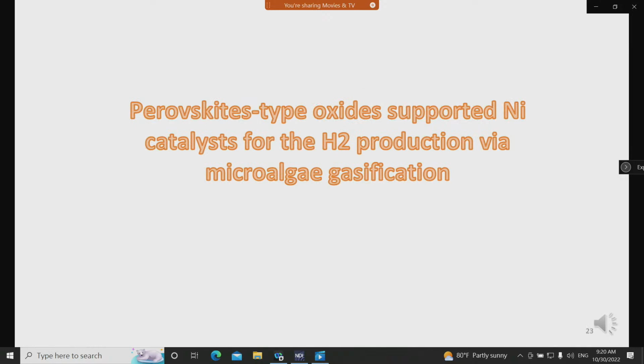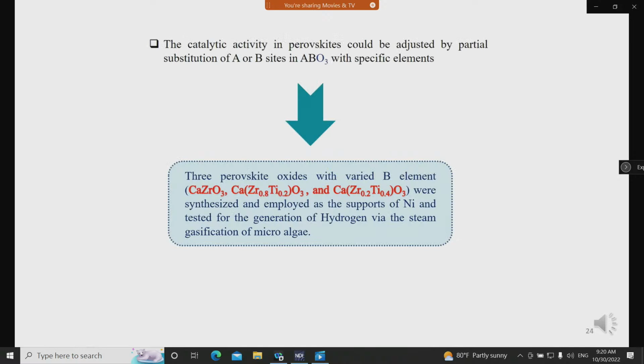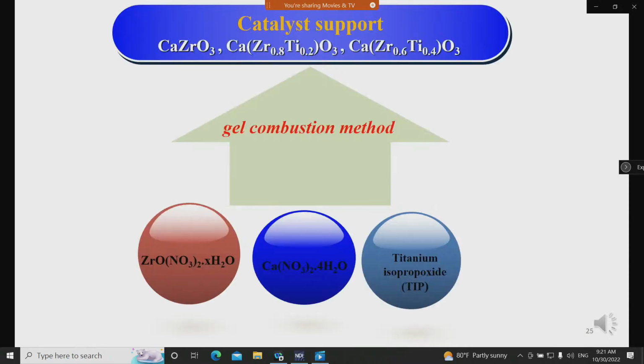From now on, I will introduce my recent research results using perovskite type catalyst. In this study, we prepared three different kinds of perovskite oxide, such as calcium zirconium oxide and calcium zirconium titanium oxide, with different ratios of zirconia to titanium. These perovskite oxides were used as supports, and nickel was impregnated on these supports. The catalyst was prepared by the gel combustion method using precursors of zirconia, calcium, and titanium.